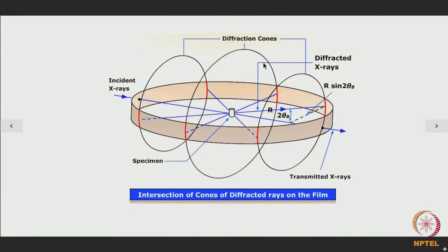Similarly, for this case also, the total integrated intensity should be considered from this entire Debye ring, but we are not doing that. Actually, we measure the intensity on unit length from each cone, so to say. Because of the arrangement and the shape of the recording film, we record only a little bit, say unit length, of the total length of a diffraction cone in every case. So, you see that because of that, what will happen?